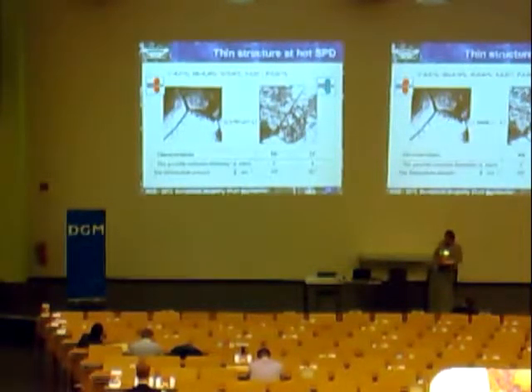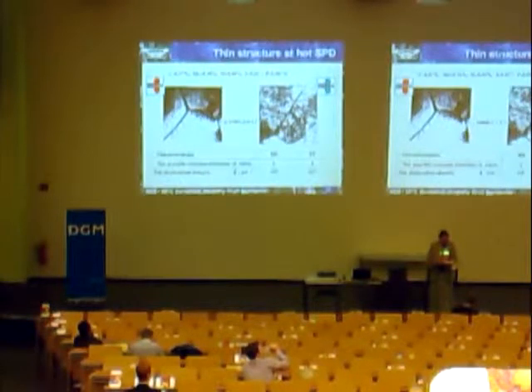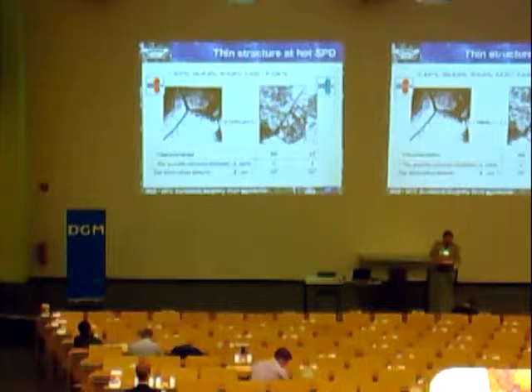The traces of dislocation flow toward grain boundaries are seen. These data bear evidence of intensified defect motion in the course of deformation by RS technology. Active motion of defects toward grain boundaries results in thickened grain boundaries. High mobility of dislocations is determined by the fact that dislocations with the screw component dominate in the material after RS technology, which can change their slip plane during deformation. This is the case of dominating high-angle boundaries in the rolling with shear process.